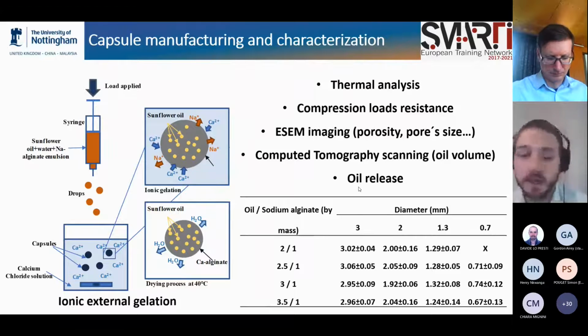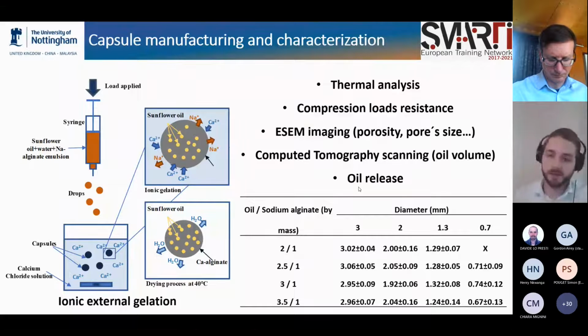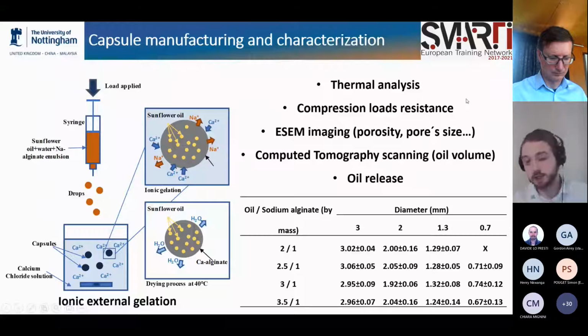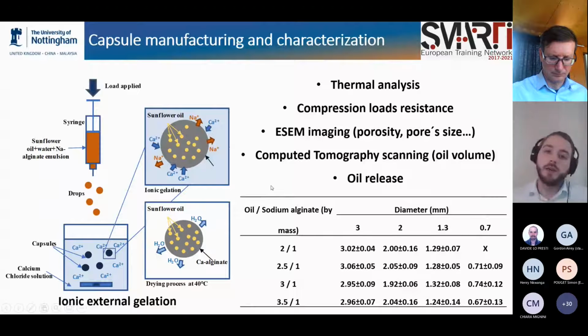To characterize the capsules and analyze the influence of the diameter and the strength of the capsule, we characterized the capsules by thermal analysis. We analyzed the compression load resistance. We did SEM imaging to analyze the porosity, the pore size of the capsules, and also see the influence of this in the self-healing. We had some computed tomography scans to assess the oil volume encapsulated, and also we can quantify the oil released by the capsules.